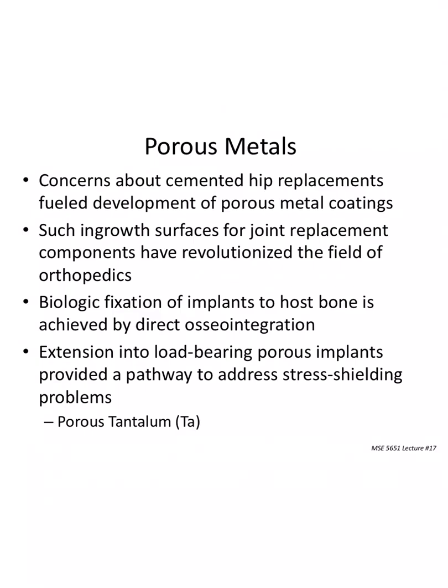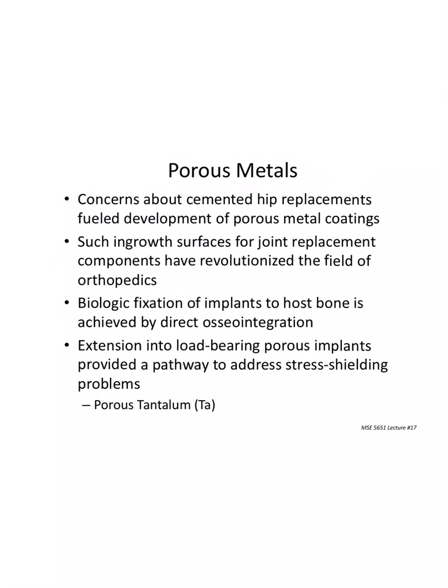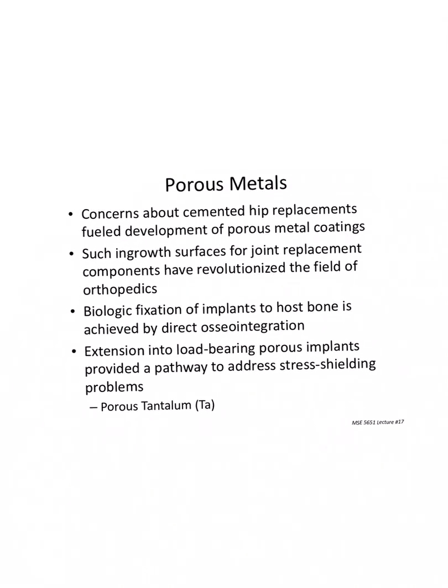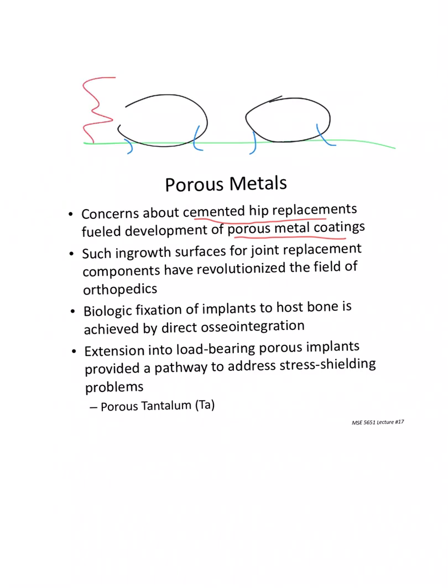All right, and so moving on to something else entirely, porous metals. And this came about because, as I mentioned at the beginning, cemented hip replacements weren't very good. All right, this is before they came up with plasma spraying, and they started looking at porous metal coatings. And we've already talked about one of those, where you sinter a sphere onto titanium or sinter a sphere onto cobalt chrome, and you make this. You have the surface, and you have titanium sitting on the surface, and you form the neck. All right. And then the bone comes along and ingrows and goes underneath these particles and gets interlocking that way.